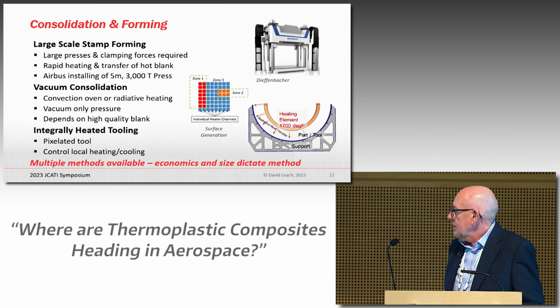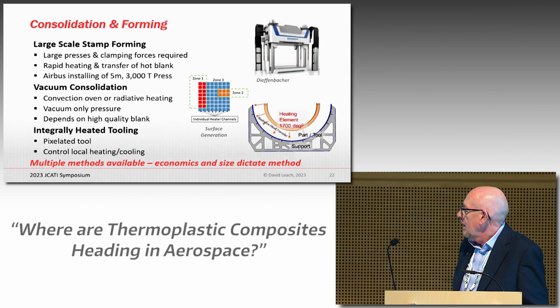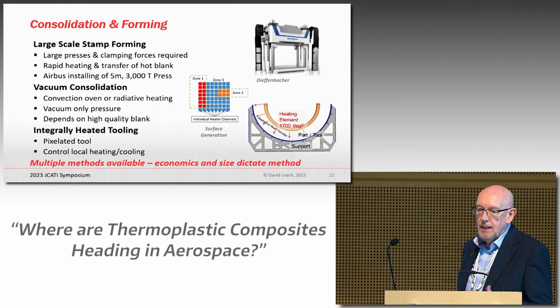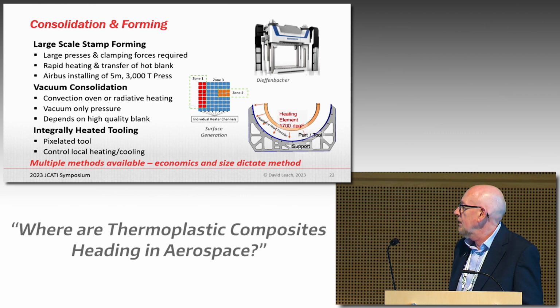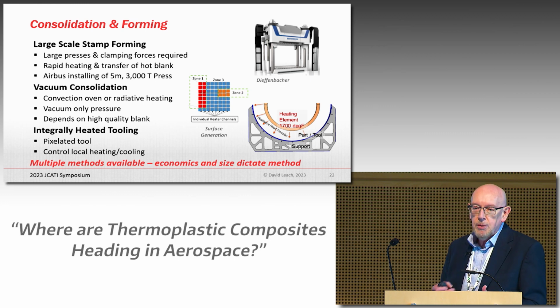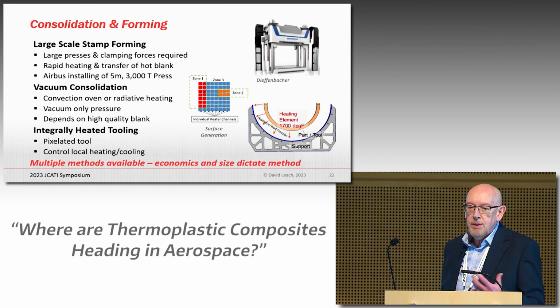But with the idea of this sort of pixelated tooling, example here from Surface Gen out of the UK, where you break the backup down into certain elements, maybe about 3 or 4 inches, and then you can heat each of those or control the temperature of those individually, either with a gas or a fluid that is actually ducted directly to that little pixel. You can both heat up and cool down quickly, and you can also control the temperature very locally and very accurately. So as an example, if there's a thicker part of structure, you would want to put more heat into that area.